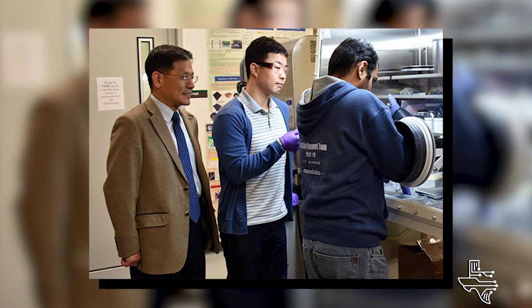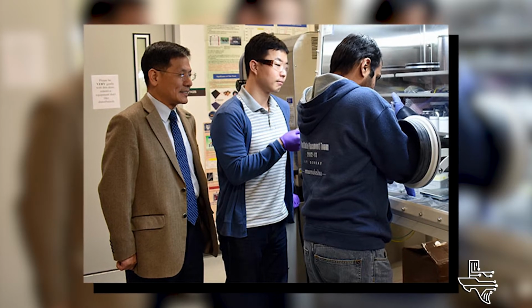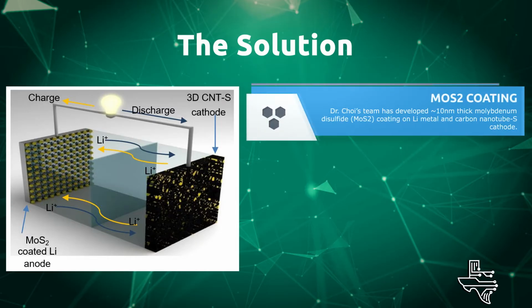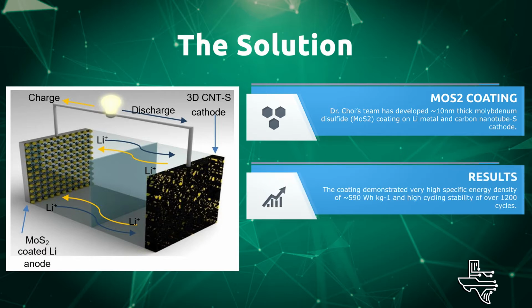So we developed a new technology using a new material, molybdenum disulfide, MoS2, which is an atomic layer material, really similar to graphite. We can control it one by one layer, individual layers of atomic thickness. By putting around 10 nanometer thickness on the lithium metal, this MoS2 presents very high lithium-ion conductivity, and we also have very high stability of the lithium metal.